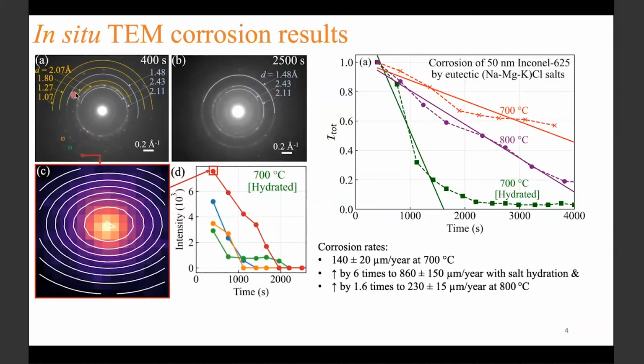So each spot around this yellow ring corresponds to the grain of the corroding containment alloy, Inconel. And the disappearance of these spots around the yellow ring at a later corrosion time qualitatively indicates that the grains are getting corroded by the molten salts. This is further analyzed quantitatively by fitting each of these spots, or each of these grains, with a 2D Gaussian function and plotting the intensity with corrosion time, which is shown here for four such different grains.